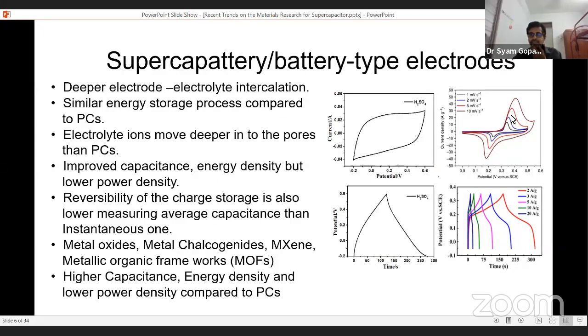But in these battery type electrodes, what we are observing is that this particular region is blank, and here the charges will be stored like this. That means in this there is no positive region, only a negative region. So the instantaneous capacitance at this region will be different compared to this region. So we cannot take the capacitance as the sum of instantaneous capacitance, but instead we take an average value and report this as specific capacitance, which is not true. That's why this term has arisen, supercap-battery, which has almost battery type behavior, while also measuring the capacitive nature of that electrode.